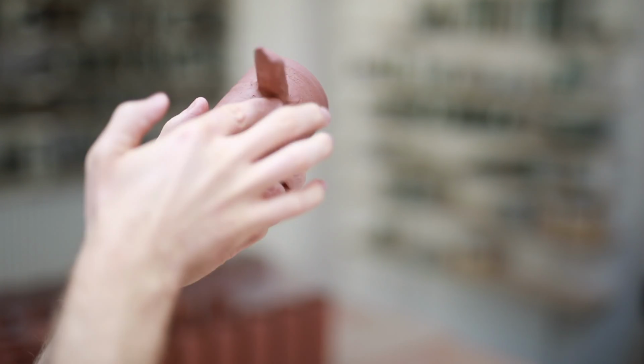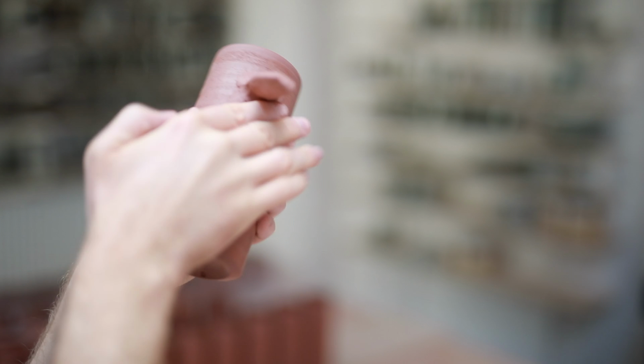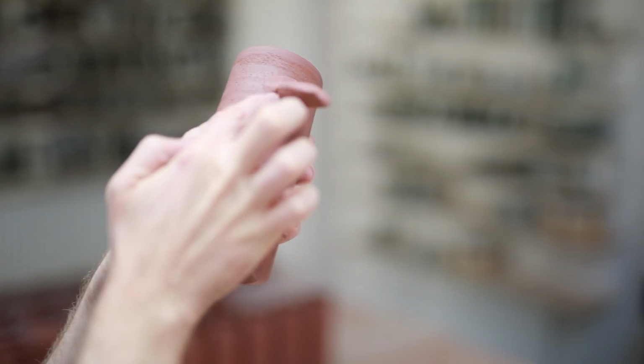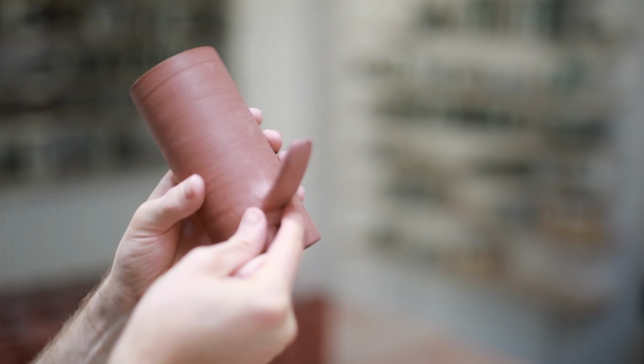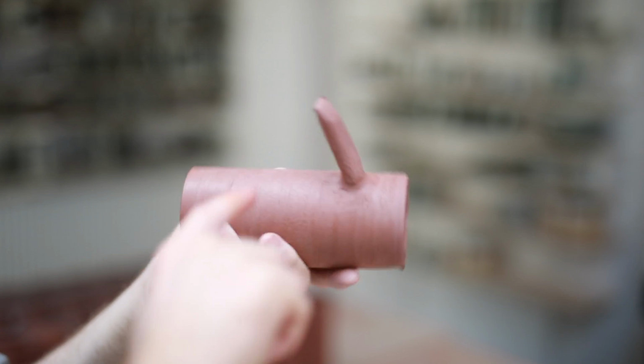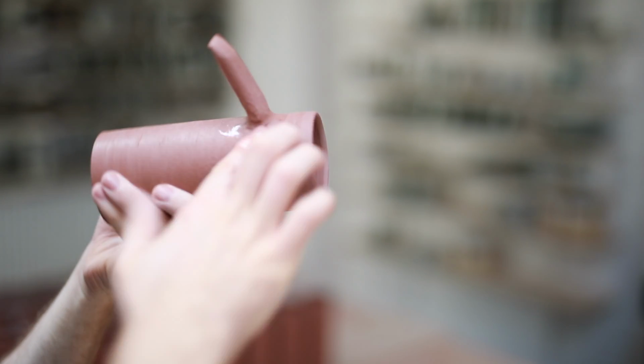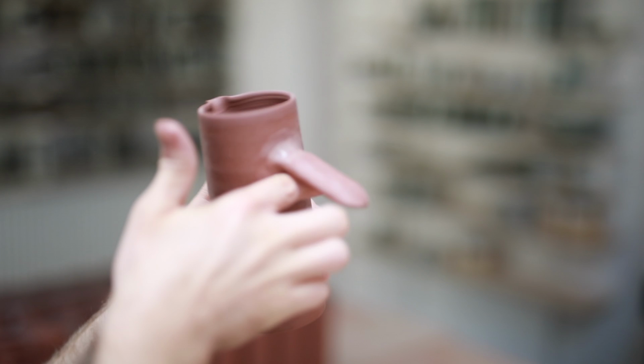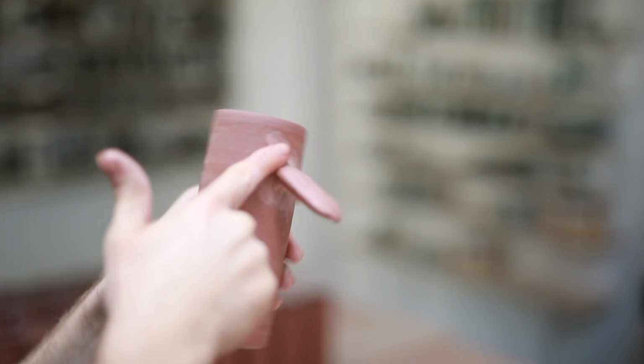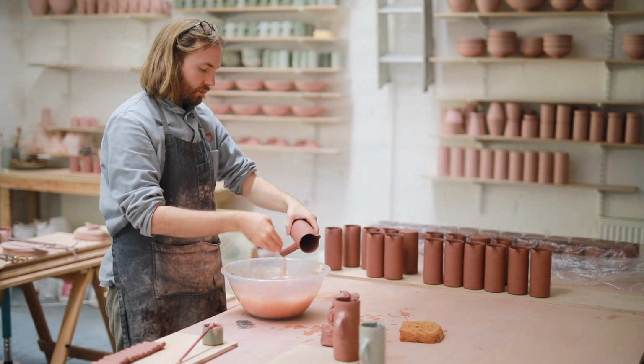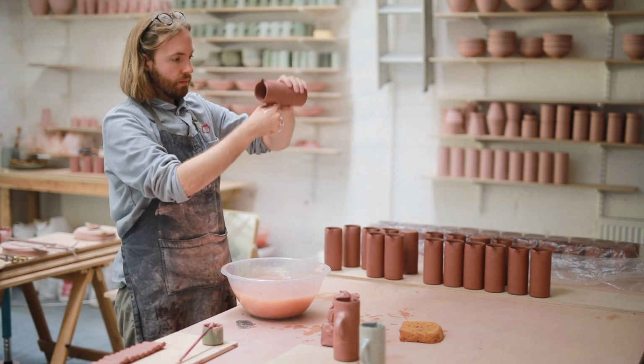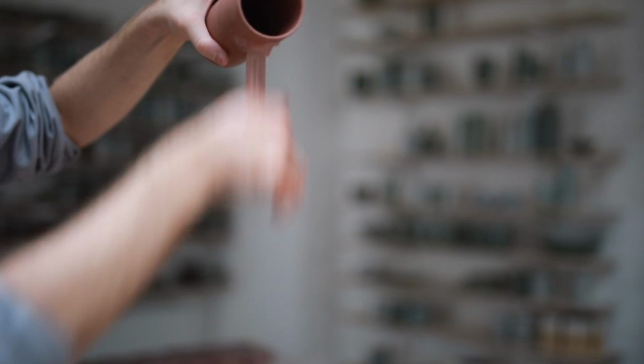I also spend a few seconds at this point neatening up the join, either by just smoothing it with a finger and then even using a little bit of water, just to make sure it's nice and tidy. I always make my handle blanks a little bigger than they need be, as I prefer to have too much material to work with rather than too little. I can always simply snip away excess handle, but there's no way of adding to it if initially it's too short. Now the real pulling and shaping begins.